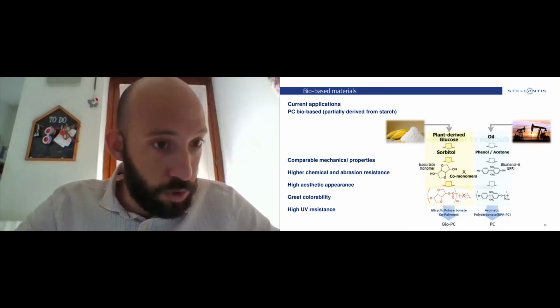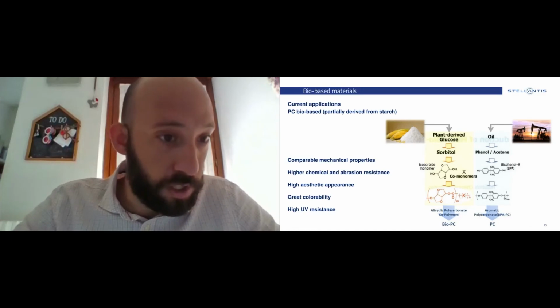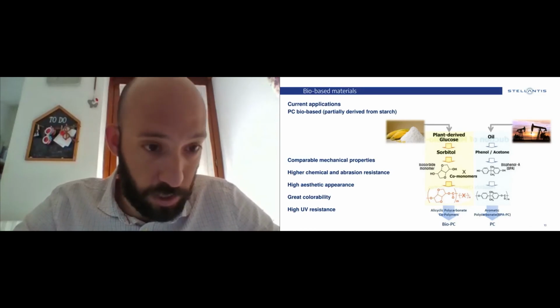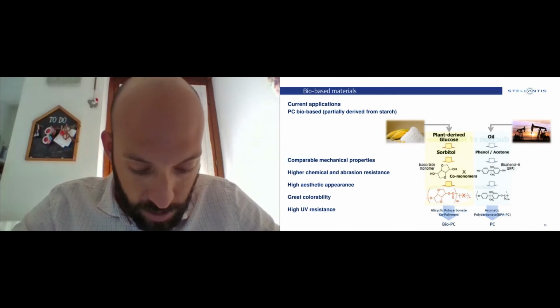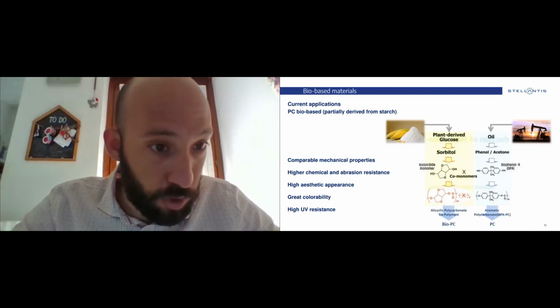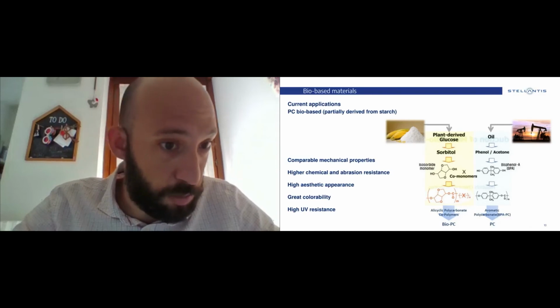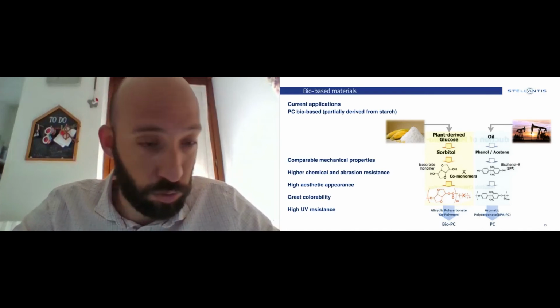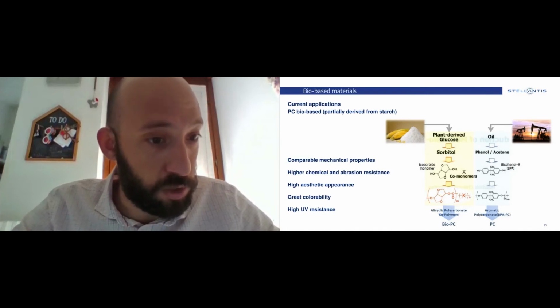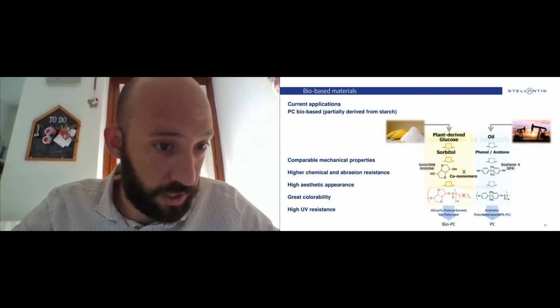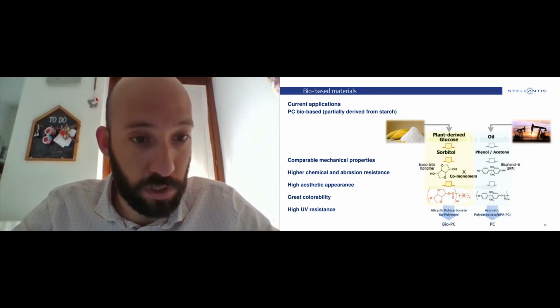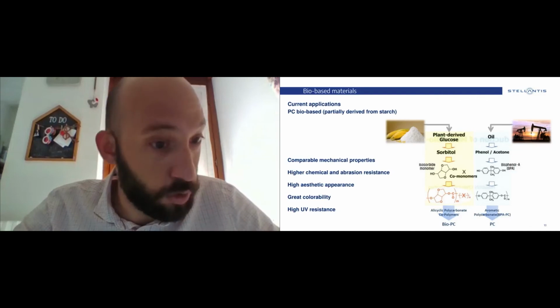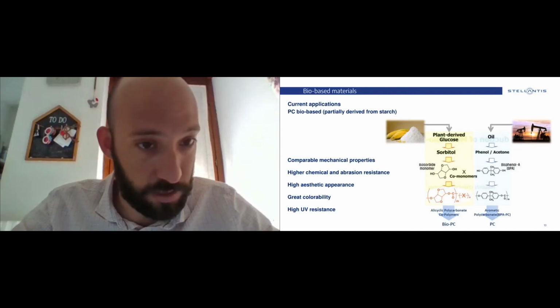The other way to use bio-based material is the biopolymers materials. In this case, I show you an example. We have a polycarbonate bio-based, which is partially derived from starch. This material has comparable mechanical properties to the virgin one, but shows higher chemical and really high abrasion resistance, with high aesthetic appearance, great colorability, and high UV resistance.